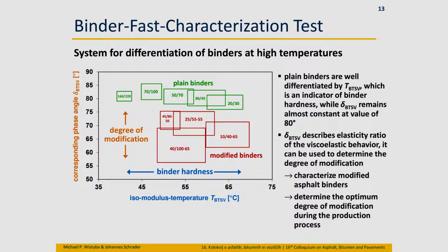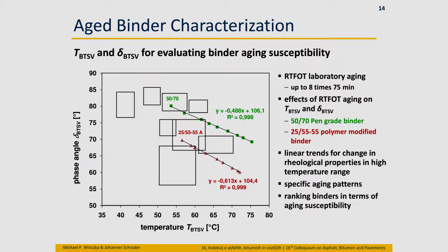A second example of how to use these parameters is to use these key parameters for evaluating binder aging. As you can see here, it's a 50/70 pen grade binder. So you see the green boxes, and you see how this first green box is developing downwards, and this is because of aging this binder, 1 time in the rolling thin film oven test, up to 8 times.